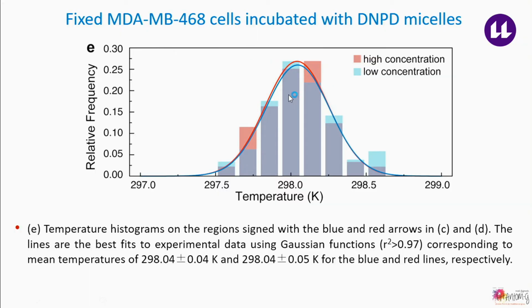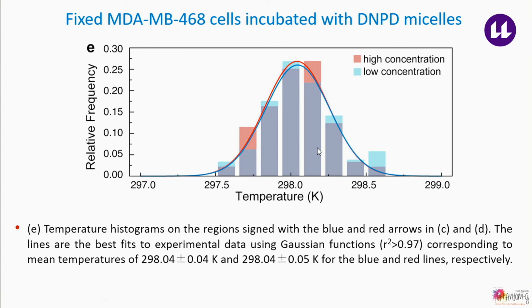So for the fixed cells incubated with the micelles, here are the results. You see the results are independent of the concentration of the particles, and we have a very narrow temperature distribution, as we expected.